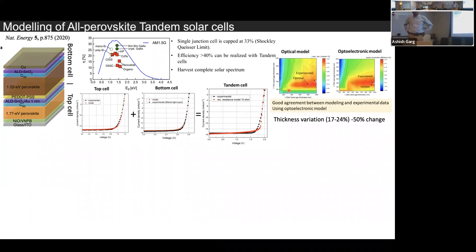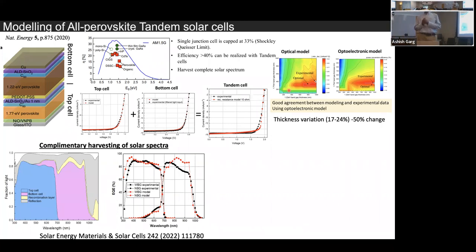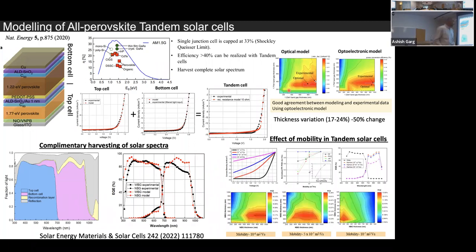So basically, what we have done is, most of the people who have modeled tandem solar cells, they have modeled them using only an optical model. So here we have brought in the concepts of drift and diffusion, combined the optical model with the optoelectronic model, and we have been able to predict a better match between the experimental efficiencies and the optimally desired efficiencies in perovskite by bringing optical and electronic models together. So we have shown that if you vary thicknesses, if you vary mobilities, you can find the sweet spots in the perovskite map. So for example, here we do the mobility variations by an order of magnitude or so, and we see how the sweet spot shifts in the perovskite solar cells, and accordingly you can choose the thicknesses of different semiconductors in the device. So this is a very nice piece of work that one of our students did recently.